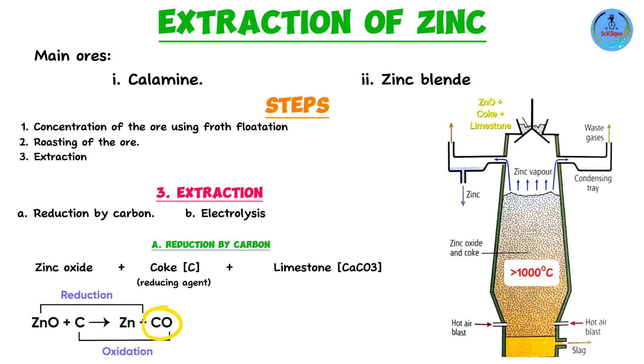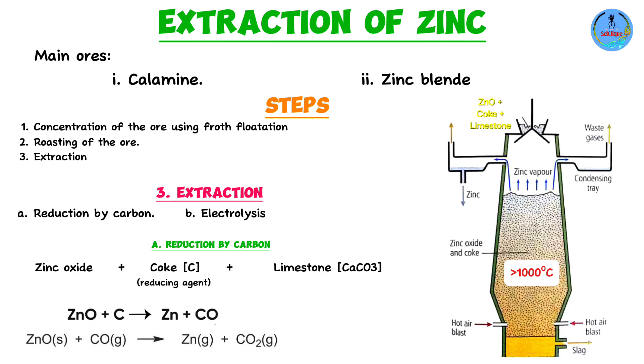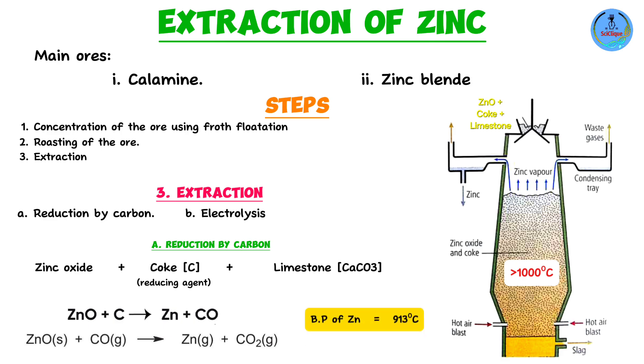The carbon monoxide (CO) gas produced is actually an advantage — it acts as a second reducing agent. Carbon monoxide also reduces some zinc oxide: ZnO + CO → Zn + CO₂. So we have two reducing agents: carbon and carbon monoxide. Note that the zinc metal in these equations is in gaseous state, because the boiling point of zinc is 913°C and furnace temperatures exceed 1000°C.